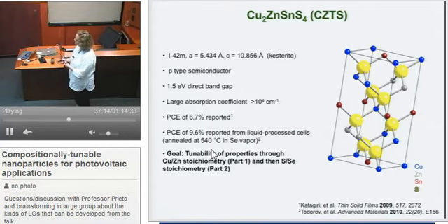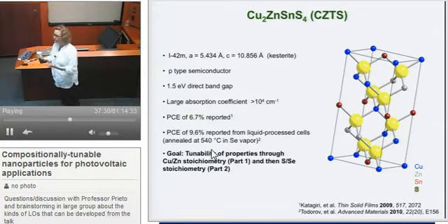One of the first reports had a pretty high one, 6.7%. Within only a year, it got up to 9.6%, and now it's actually above 11%. And so I was interested because without even knowing very much about the compound, it's already performing pretty well. Now, the challenge here is that this 9.6% cell was processed out of liquid solution. And people were excited about that because the thought was, instead of the traditional solid-state methods of very high temperatures or using something like chemical vapor deposition to deposit a film, which would be really expensive, could we